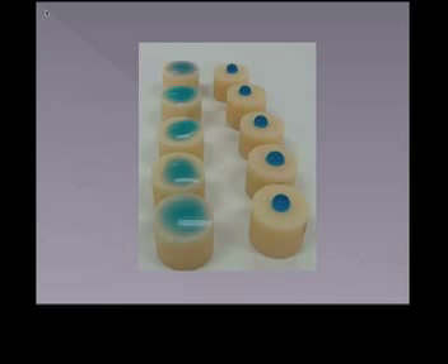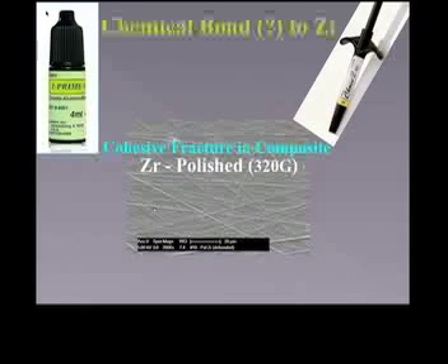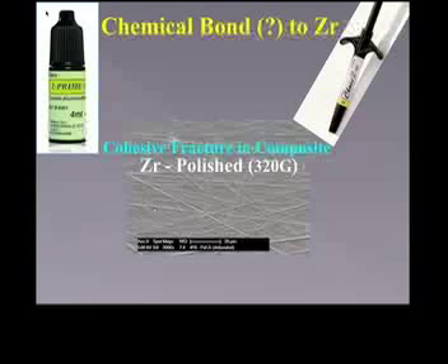The next slide shows covalency proven by cohesive failures. Basically, you want to make sure you prime these surfaces so that you get the best hydrophobic surface that you can. Again, we're going to go through the steps: mild sandblasting with aluminum oxide on these zirconia bonding restorations.